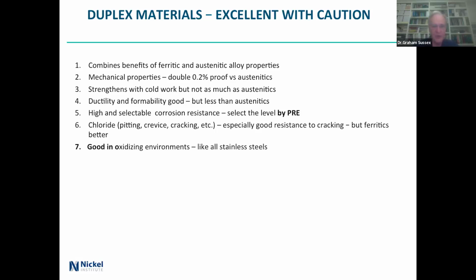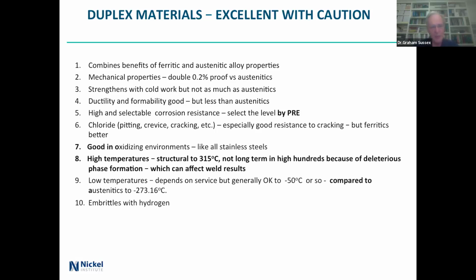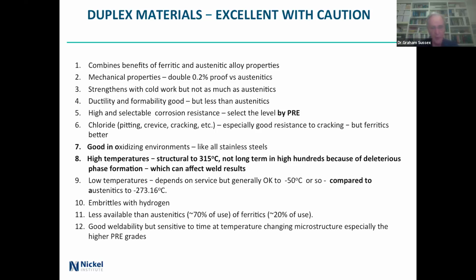Ferritics are going to be better. Very good in oxidizing environments like all stainlesses. High temperatures, well, not really. Structural up to about 315 C, although some people hold it to about 280. But you don't go putting in the high hundreds for a long time, and I don't mean hours, I mean minutes, because you get bad phases forming. That's something that can be a problem with welds, of course, and we'll talk about that in a few minutes. Low temperatures, minus 50 or so, nothing like the austenitics, of course, going down to absolute zero, minus 273.16. And the 0.16 is apparently very important. Embrittles with hydrogen, and it's less available than the austenitics. Austenitics, roughly about 70% in the world, and the ferritics, 20% or a bit more, and the duplexes have to fit in there. Quite good weldability, but it's a bit sensitive to time at temperature because of getting extra phases, and we'll talk about that.